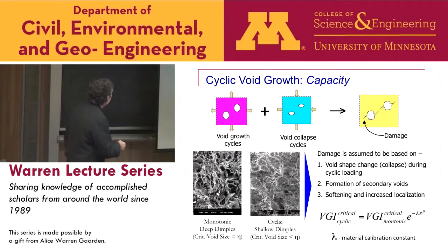The other piece, apart from the voids growing and shrinking under negative loading, is that after a while you can imagine the voids don't purely shrink down. They change shape and collapse during the compression cycles.